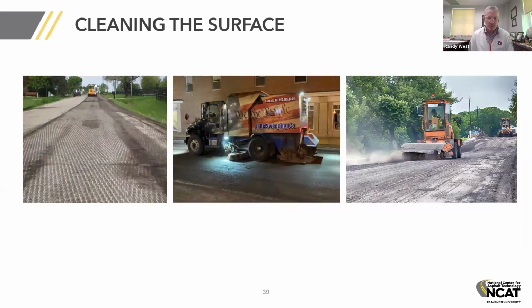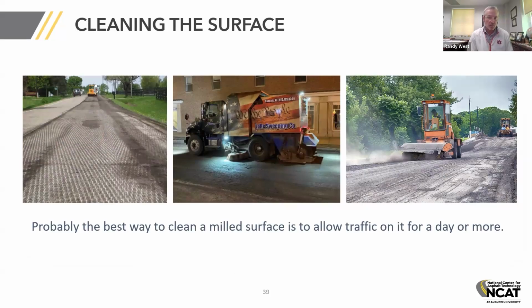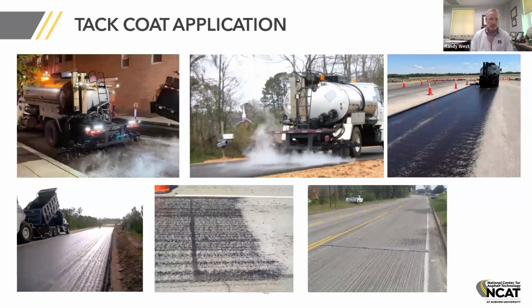Cleaning the surface can also be an issue. And I mentioned in New Jersey, my hypothesis is that we weren't getting the surfaces well cleaned. And so another hypothesis is that probably the best way to clean a milled surface is to allow traffic on it for a day or more. Traffic does a really nice job of cleaning off pavements. Sometimes you don't have that luxury, but I do think that is a good way to clean surfaces. There's lots of good information on tack coat applications and how to measure that, and I'm not going to go into much detail here, but you probably all have seen variations.